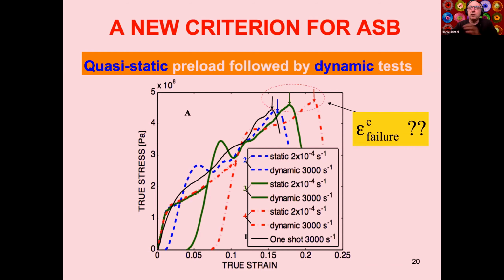So is there a critical strain at failure? If we take into account the overall thermomechanical history of our material, we cannot define a unique failure strain. Let me translate that into engineering terms. I am machining an armor plate, and I'm cold rolling the plate. And then I'm asking you, is that cold rolled plate or hot rolled plate going to perform as well as a plate that was not rolled before? And this is what I would say, this is the rolling, this quasi-static pre-strain. So at that point, we wonder, what do we do with those results? In fact, there's no unique failure strain, and we have to take into account the quasi-static preload history.